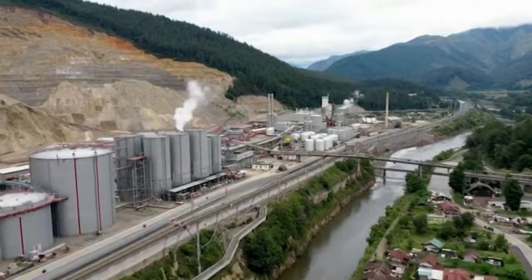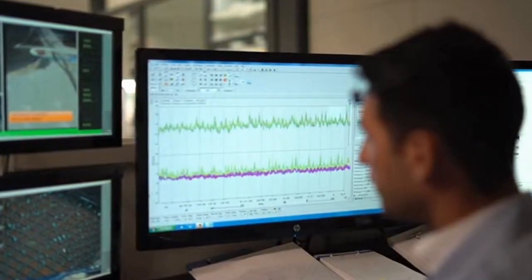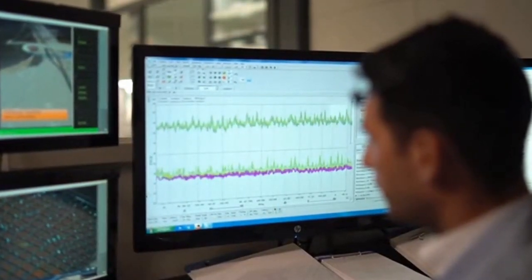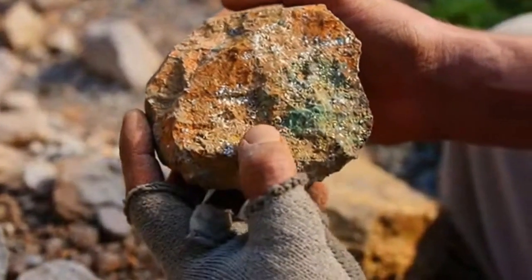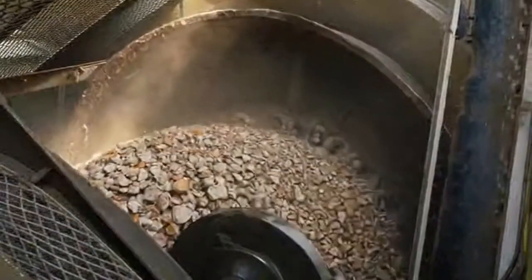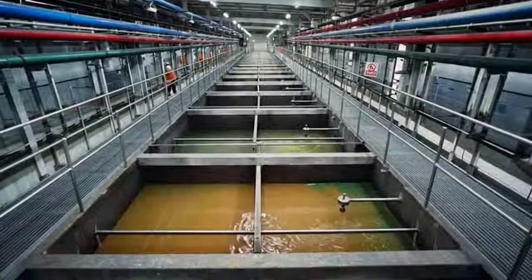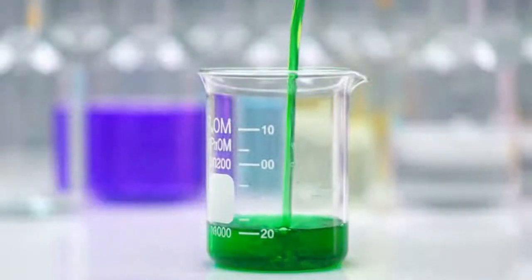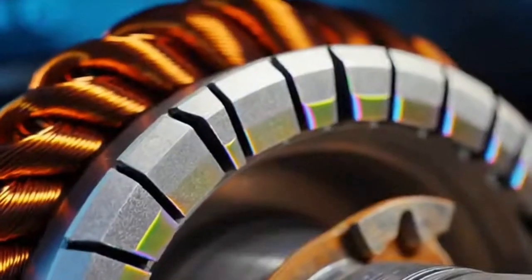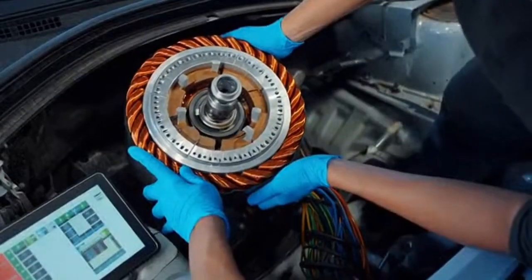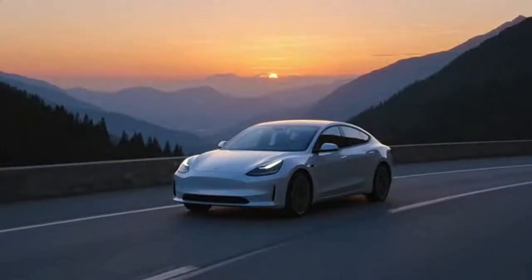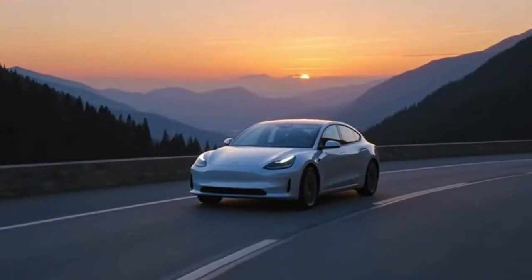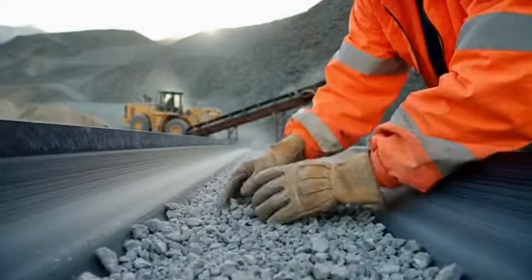Every step from oxide to finished magnet has a shadow market in scrap. In-process trimmings from machining are valuable because the alloy is valuable, and hydrogen decrepitation, obligingly, works on scrap as well as it works on ribbons. You can crack and remill, then blend back into powder feeds if you keep oxygen and carbon under control. End-of-life magnets are a harder story because they arrive contaminated with adhesives, plating, and the sins of their prior housing. Here again, a blend with praseodymium helps practically, because the market does not demand you separate at the element level to reuse.